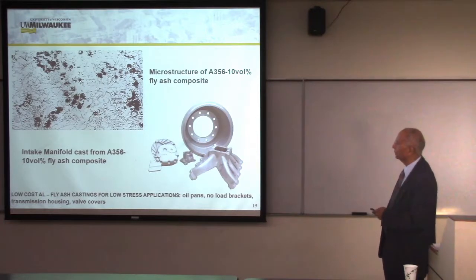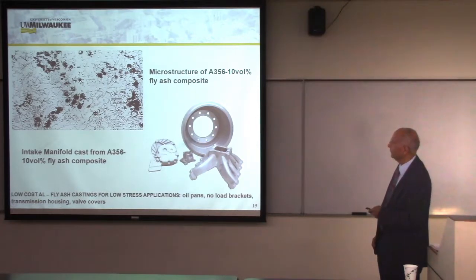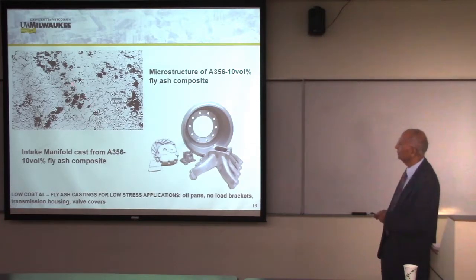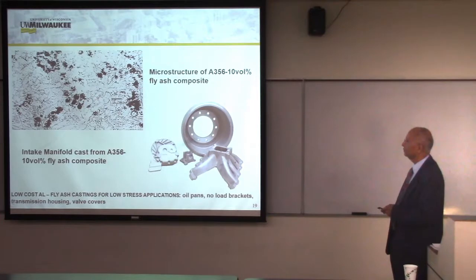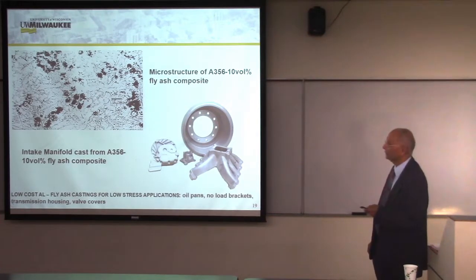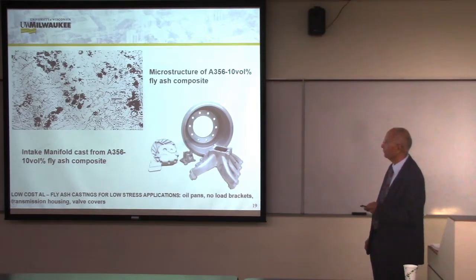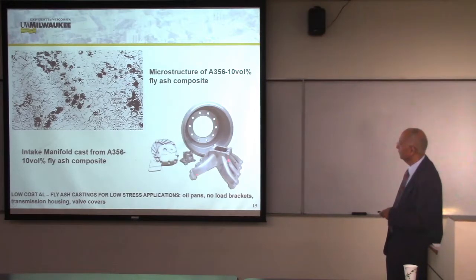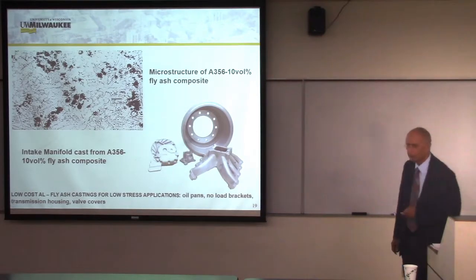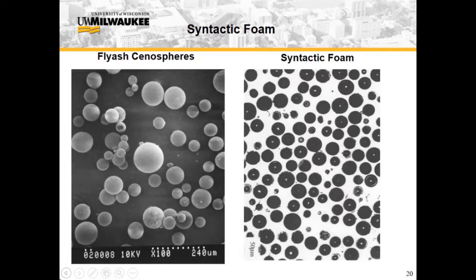I did talk about low-cost fly ash filled metal matrix composite casting, and here is an example: the fly ash particles dispersed in the matrix of cast aluminum. And Indian fly ash is F fly ash, which is more suitable than C fly ash for dispersion in aluminum castings. And incorporating fly ash in aluminum makes it cheaper, it makes it lower in density, lower weight, and it increases the wear resistance and decreases the coefficient of expansion. And here are a number of castings made in aluminum fly ash, including intake manifolds, including a magnesium fly ash casting, and an oil pan cover for small engines. So these things have been used, and I believe they can be manufactured.